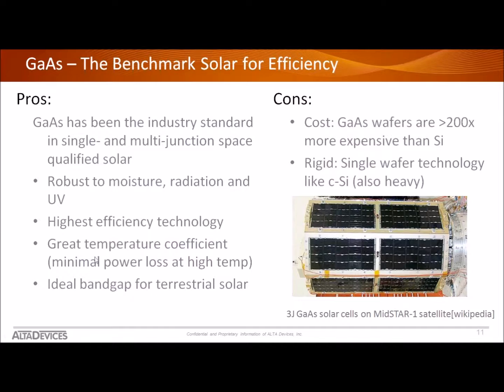And it is perfectly matched as far as our band gap discussion for collecting light at the surface of the Earth. The biggest disadvantages, and why gallium arsenide, despite its penetration in the space industry and in concentrated farms and other places, is that the biggest con is its cost. Gallium arsenide wafers are 200 times more expensive than silicon wafers. They're also rigid. They're a single wafer technology, which means that they're very pure. They don't suffer from a lot of defect problems, but they're very heavy.